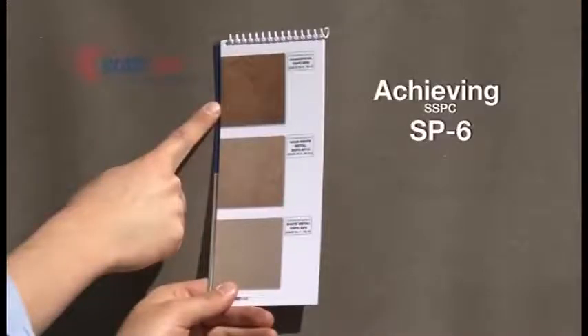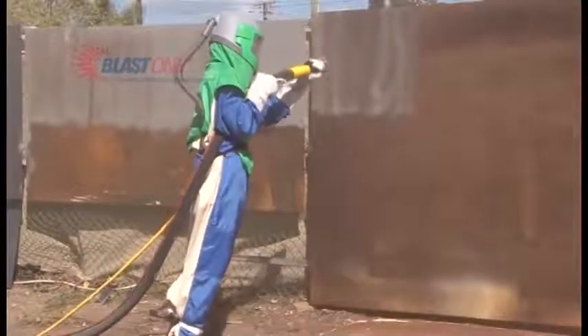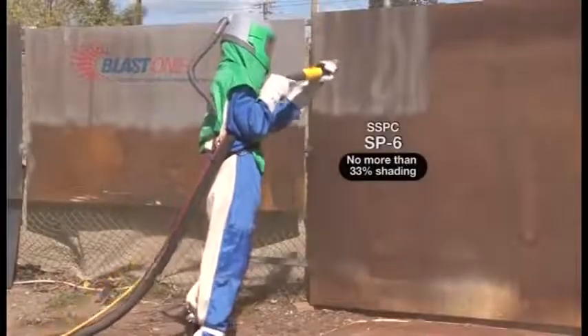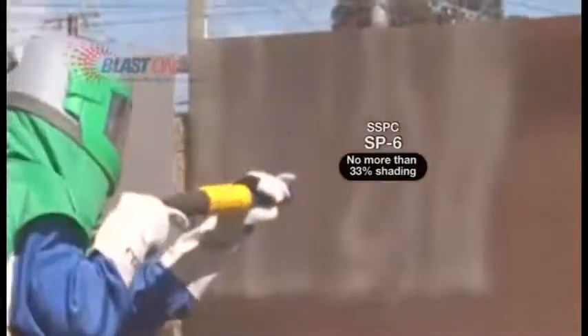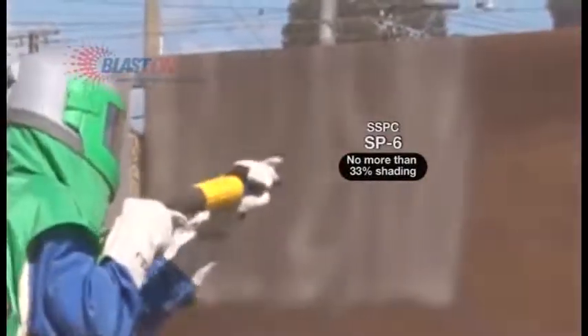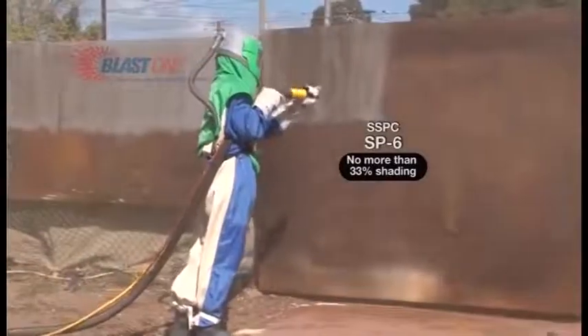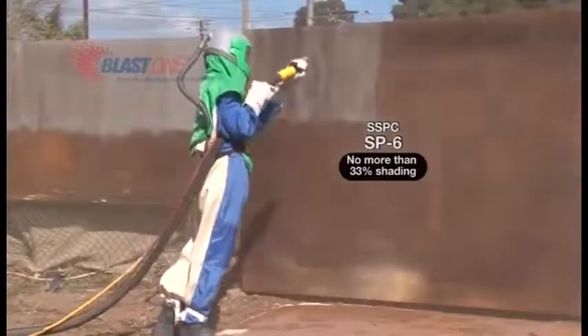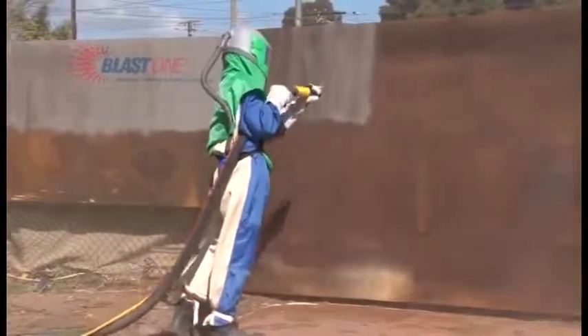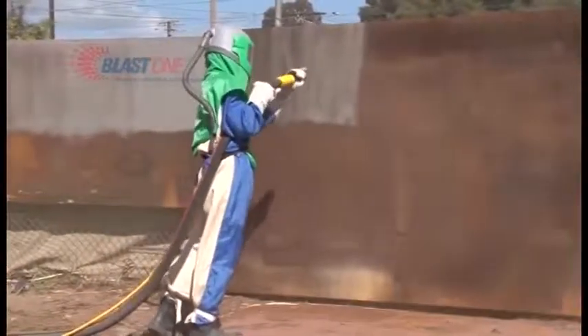How to achieve an SSPC SP6. The specification for SP6 is the removal of all loose surface contaminants, leaving no more than a 33% shading within the blast pattern. To achieve SP6 on a grade C substrate, the blaster moves relatively quickly, but yet slower than he did on grade A or B. This is to ensure that there is no more than 33% shading. With less than 33% shading, substrate C specifications for SP6 have been accomplished.